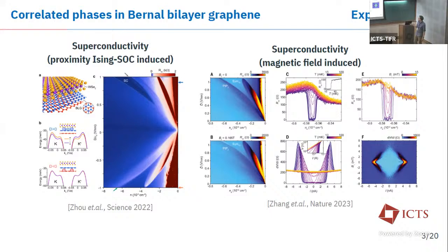And the other observation is magnetic field-induced superconductivity. This is, in fact, only a very tiny region in the phase diagram. Here you have, again, the doping and electric field phase diagram under a magnetic field. And you see that somewhere in between those magnetic symmetry breaking phases, you have a superconductor that pops up. And as the phase is tiny and very close by to some magnetically ordered phases, you would expect that it could be a weak coupling electron-electron interaction-driven superconductor.